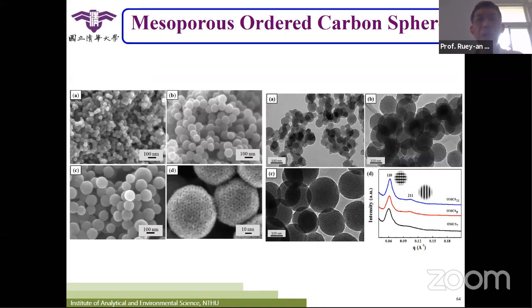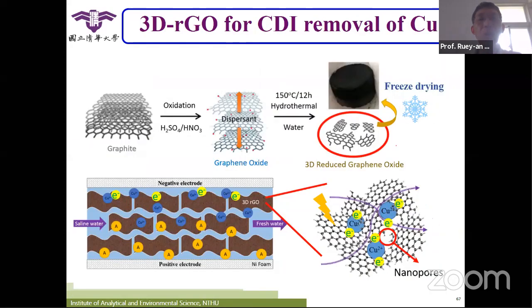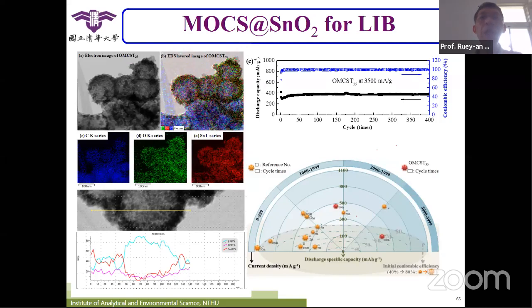We also tried to use the mesoporous carbon spheres. We mentioned it previously, so I would like to do it very quickly. We put the tin oxide on the surface. Outside, actually, here is the tin oxide, the black one.